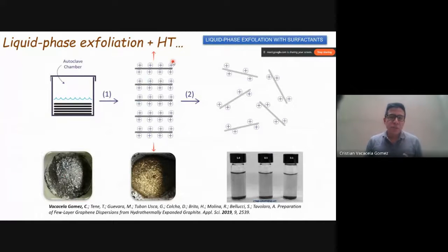Another technique is not only to sonicate graphite. Before the sonication, we can also do an extra process. For example, in our group, we are working with expanded graphite, or we are creating our own expanded graphite by using a hydrothermal exfoliation, which means we have an autoclave chamber. Inside here, we introduce graphite, water, and a surfactant. We increase the temperature to more than 150 centigrade for 10 to 24 hours, and we increase the pressure, and we induce the intercalation of the surfactants. That way we have a hydrothermal expanded graphite that, subjected to a sonication process, makes it easy to prepare graphene, few layer graphene dispersion, in a reduced sonication time. For example, less than 1 to 2 hours.